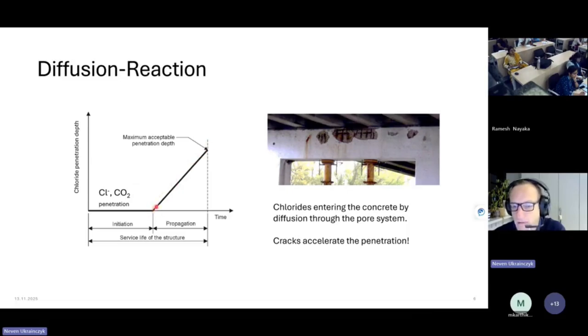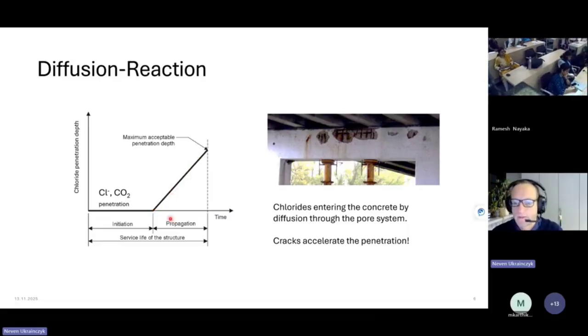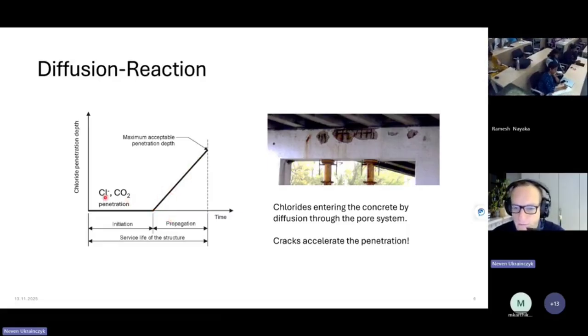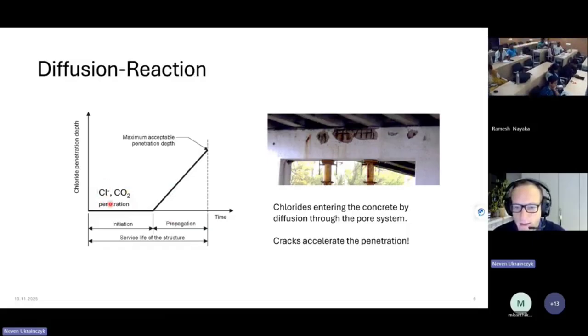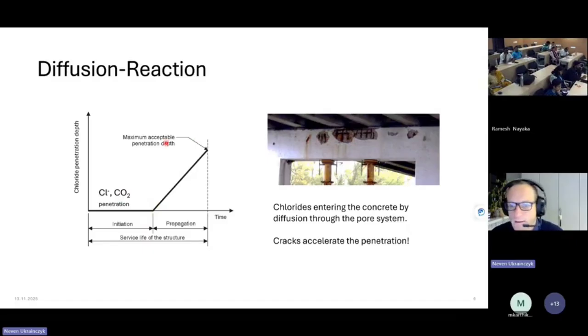And also the accumulation of chlorides at the steel bar level, we have the propagation. Because I will show you the mechanism, chlorides act as accelerators, they depassivate the steel. I will show the chemistry behind. So when we reach the maximum acceptable penetration depth, or the amounts, this is then the end of the service life of the structure.